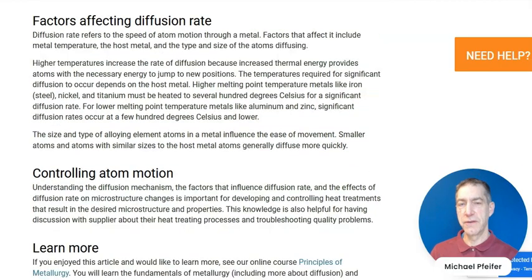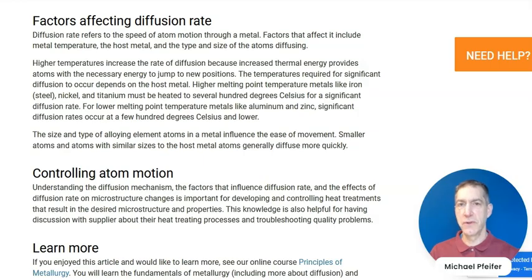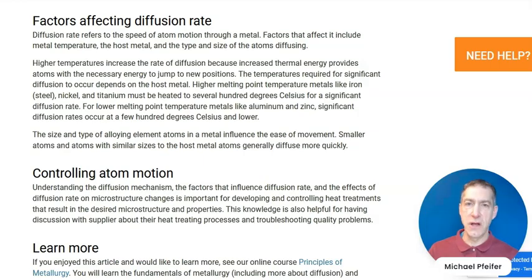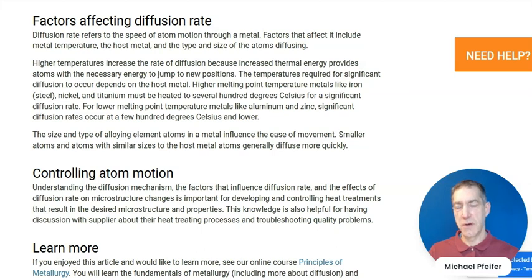There are a few different factors that influence the diffusion rate. Temperature will influence the diffusion rate — the higher the temperature of a metal, the faster the atoms are able to move around and the faster the changes will occur inside of the metal. Also, the type of metal is important. If it's a high-temperature metal, it has to be heated to a higher temperature in order to get significant diffusion. Those can include iron alloys, nickel alloys, and titanium alloys. Lower-temperature alloys such as aluminum and zinc alloys require lower temperatures to get significant diffusion. In fact, in aluminum alloys, there's even diffusion at room temperature — for precipitation strengthening, precipitates form at room temperature due to the diffusion that occurs inside of the aluminum alloys.